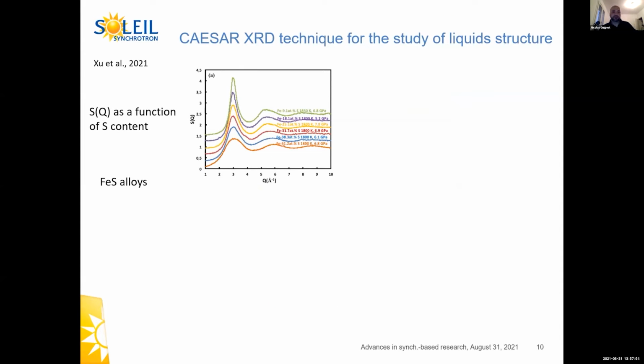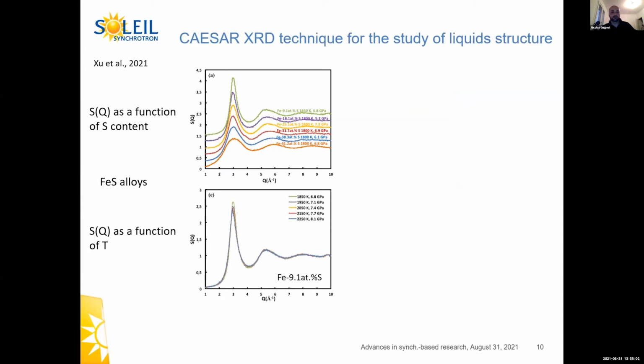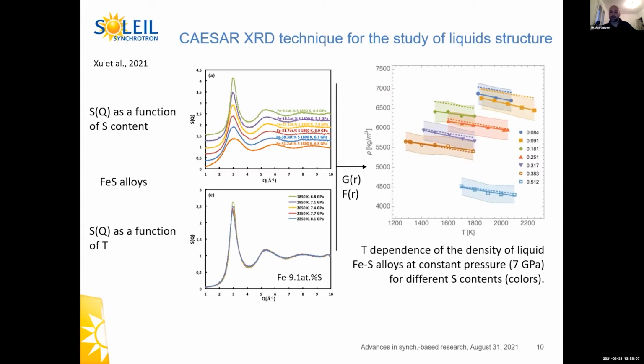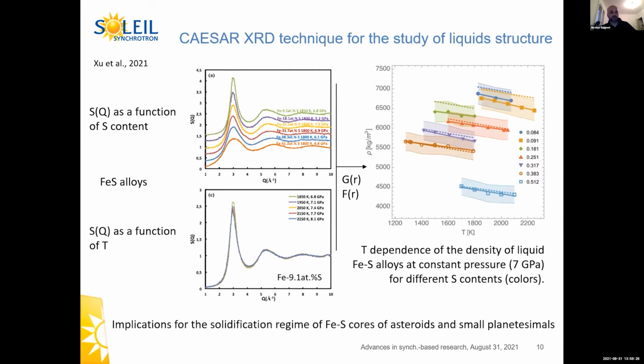So Xu and collaborators did these measurements for different sulfur contents and also at different temperatures. So you have all the I of Qs. And from this data, they could get the G of R, F of R, and get the densities. And here you have the temperature dependence, so thermal expansion of the liquid iron sulfide alloys at constant pressure, here at 7 GPa, for different sulfur contents. So this has implications for the solidification regime of iron sulfide cores of asteroids and small planetesimals.